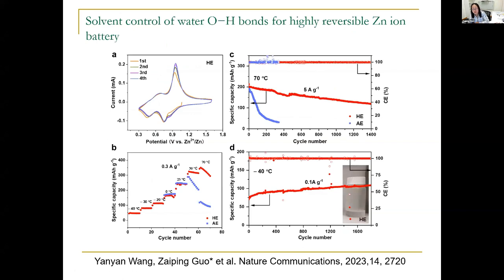And with this hybrid electrolyte, the zinc vanadium pentoxide full cell can be charged and discharged at high temperature, 70 degrees, for 1,400 cycles. And it also can be charged and discharged at minus 40 degrees. You can see nearly 1,600 cycles. The capacity is still quite stable. There's no obvious capacity fading. So basically, by using this electrolyte, the zinc battery can be charged and discharged over a very wide temperature range.